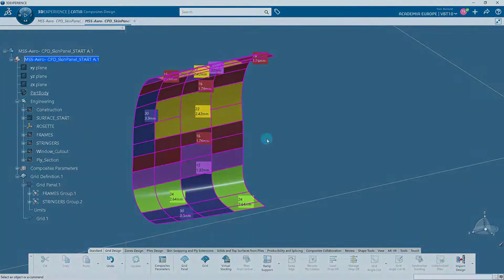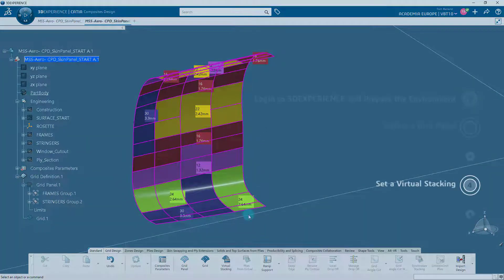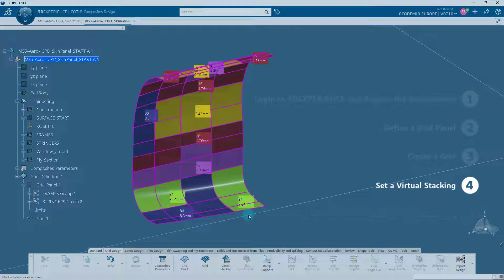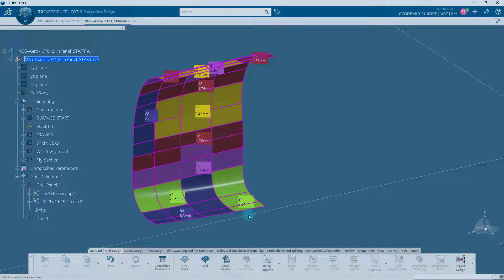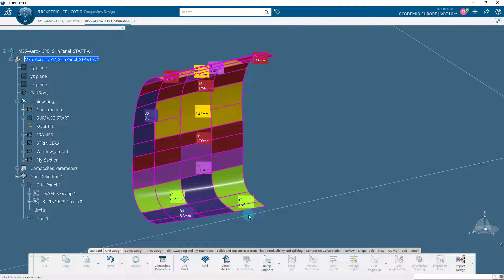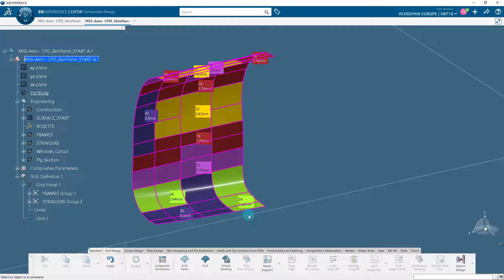After creating the grid, virtual stacking is used to transition the preliminary design grid definition into detailed design plies that can be manufactured. This step is done by the software combining the neighboring cells covered by the same layers, the same material, and with the same orientation, to create ply sequences. Besides, composite design rules are also integrated by the software at this step, such as symmetrically balanced, as well as full plies on external layers.